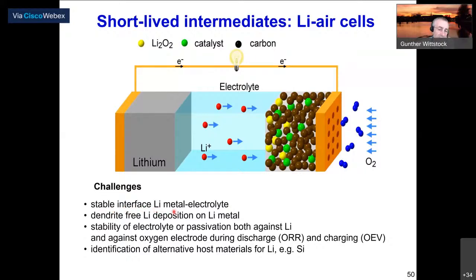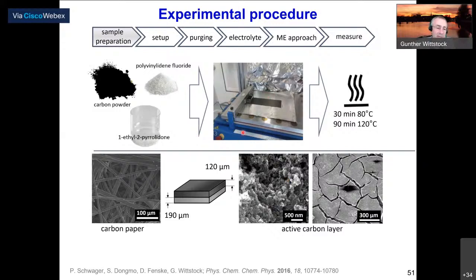We need to have a stable interface at the lithium metal electrode. Dendrite-free lithium deposition is a challenge. Stability of the electrolyte must be ensured both with respect to the very reducing lithium, but also to the very oxidizing oxygen and reactive oxygen species. That could maybe be done by the identification of host materials for lithium like silicon and other tin alloys and things like that. So let's first turn to the gas diffusion electrode.